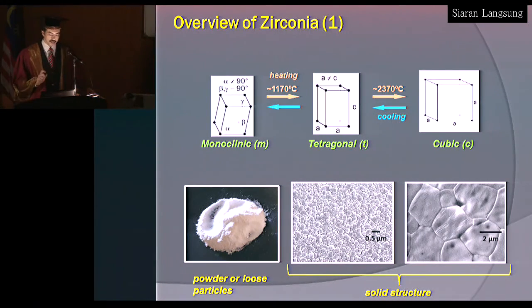Now, what is important to see in this structure, in order to appreciate why LTD takes place, is that if you look at the dimension, the axis dimensions a and c, and the angles, they are not the same. Now, as transformation proceeds from monoclinic to cubic, there is a volume shrinkage, and there is a structural change from powdery loose particle into a solid structure.